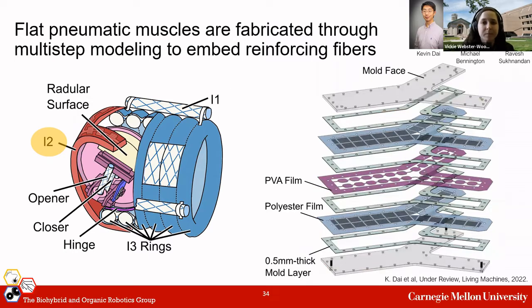In order to do that, we had to make some modifications from the original work reported in the literature. We created a Y-shaped mold and sequentially assembled and molded our actuator. Rather than using embedded Kevlar fibers for the reinforcing fibers, we found that those delaminated and tore out pretty easily. So the guys had a great idea to use a Silhouette Portrait 2 electronic cutter and cut polyester films in order to reinforce the actuator. In doing that, they were able to add these sequentially to this stacked mold design and then cast elastomer into the cavity as each layer is added. After curing the whole stack, they're able to remove the mold and dissolve the PVA films with deionized water. And this gives us this flat I2 actuator.